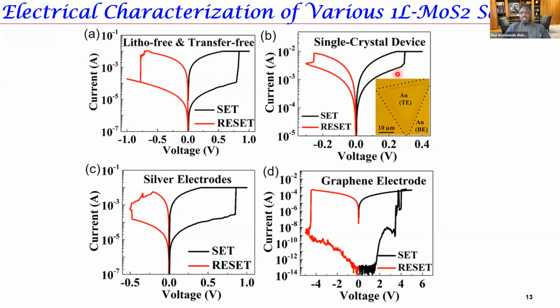So we went through significant effort to make devices on single crystal. As those of you doing experiments know, you can grow these almost perfect triangles of MoS2 that are large enough, and then one can deposit a top electrode on top of that. Again, we see this emergence of memory effect.